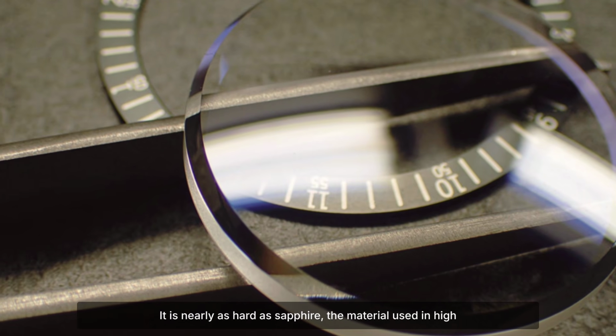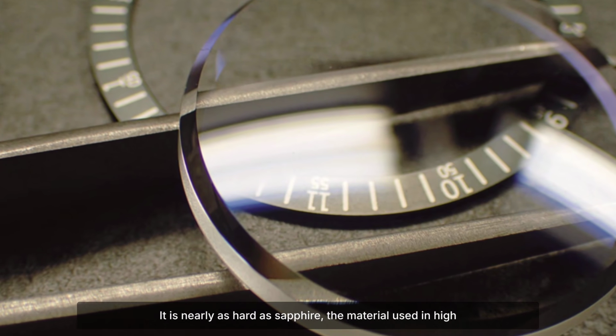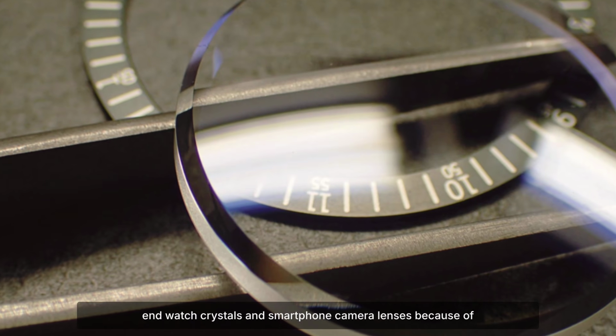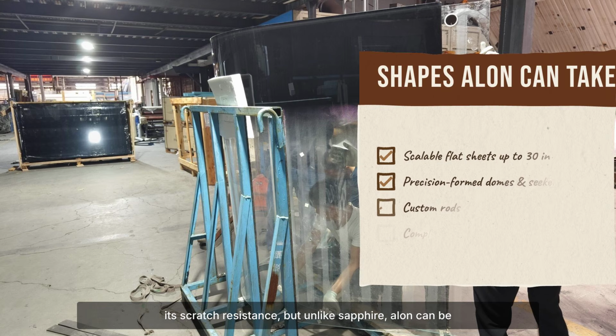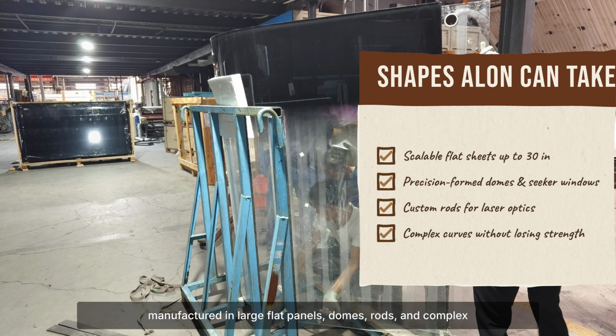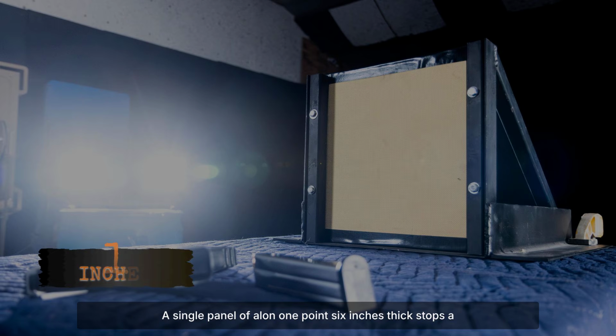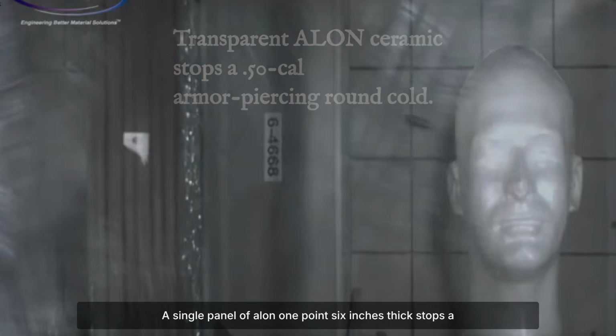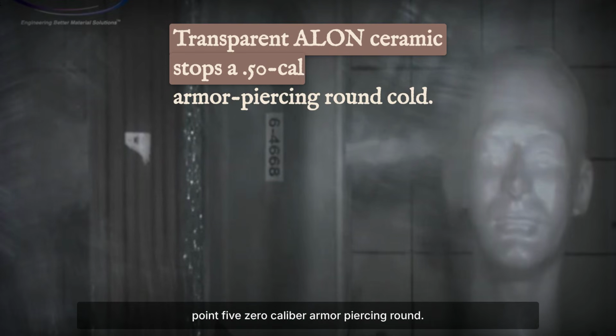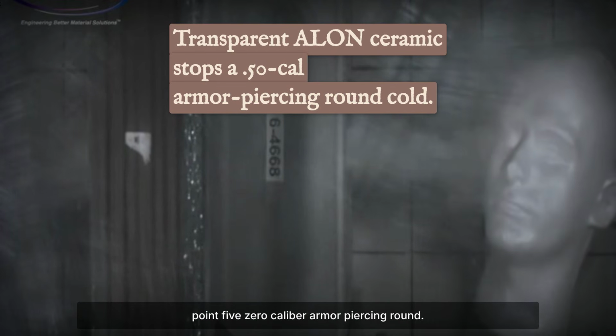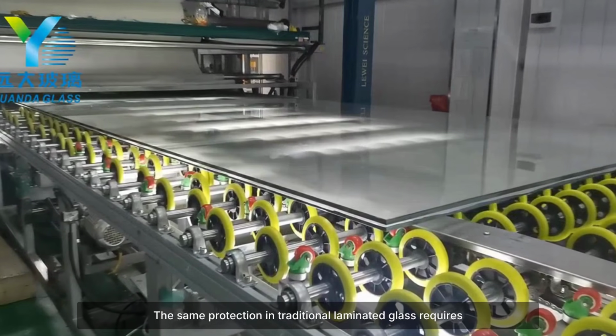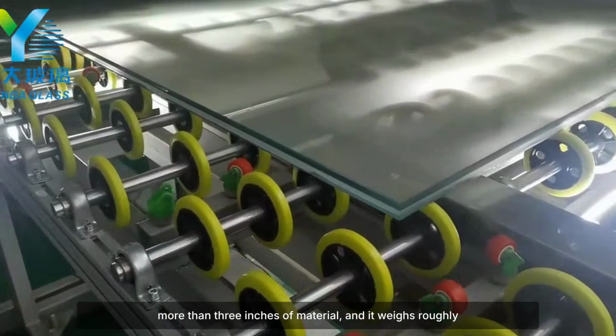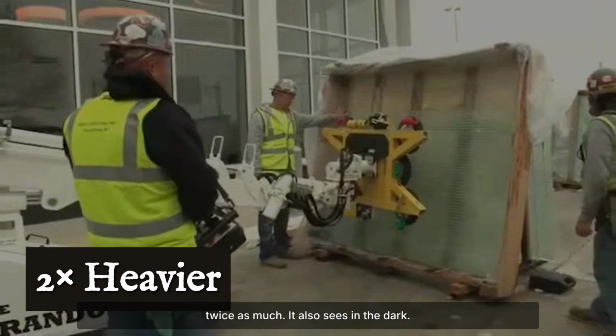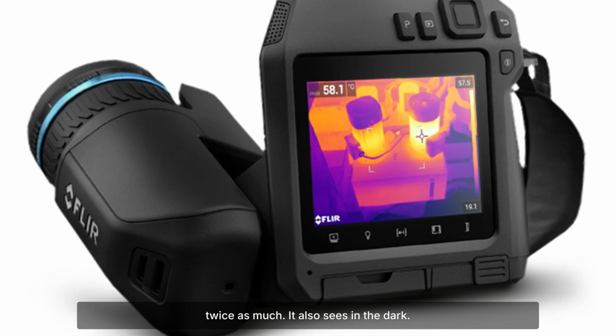It is nearly as hard as sapphire, the material used in high-end watch crystals and smartphone camera lenses because of its scratch resistance. But unlike sapphire, Alon can be manufactured in large, flat panels, domes, rods, and complex curved shapes. A single panel of Alon 1.6 inches thick stops a .50 caliber armor-piercing round. The same protection in traditional laminated glass requires more than 3 inches of material, and it weighs roughly twice as much. It also sees in the dark.